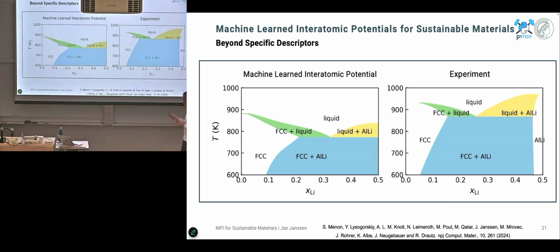And for these machine learned potentials, it's usually enough to just do a perturbative approach. So from our trajectory, we pick a subset of configurations and check how big the difference is. If it's below the precision level that we aim for, then we're fine. But you can really have ab initio precision on all of these points.